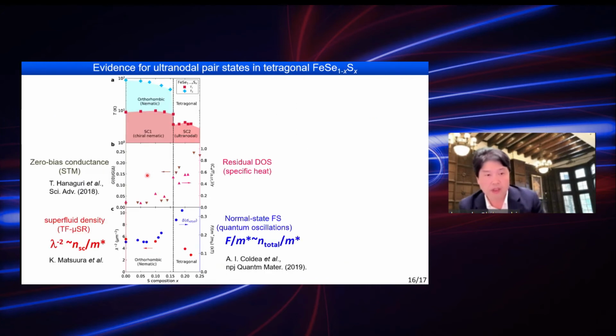So this is a summary of what we have measured. The upper panel shows again the electronic phase diagram. The blue points are the nematic phase transition temperature, and red is the superconducting transition, which shows a jump. And we have a lower Tc on the tetragonal side.